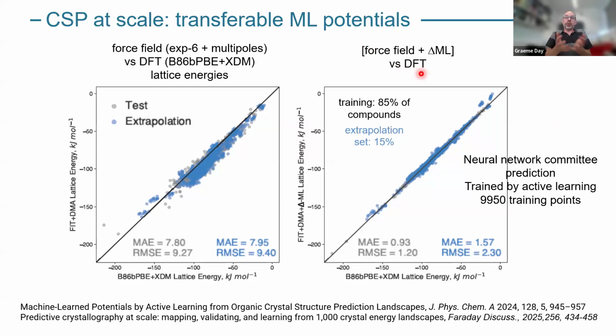And the reason we want to be able to do this is we want to be able to do it for any new molecule. And so we're now going to train it not just on a single CSP landscape, but on over 1,000 CSP landscapes. So what we did was we took 85% of the molecules in that study and all of the predicted crystal structures, and we put them into training. Okay, and we withheld then 15% of the molecules as a test set. Okay. Of the ones we put into training, we only took 9 structures per landscape and did our density functional theory calculations at this level of theory here.